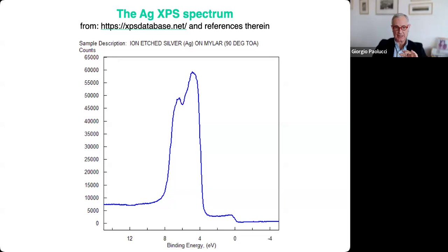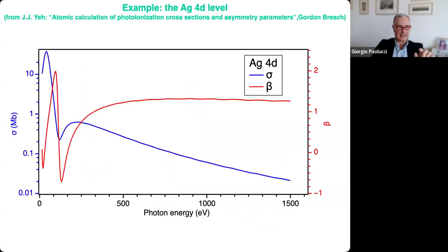And you can see that between 0 and say 3.8 eV, you get this monotonic behavior, which is what you expect from a simple metal, because that reminds you of the Fermi-Dirac distribution. And then you get the 4d levels, which are very localized in energy. The 4d level of silver has a peculiar behavior as a function of photon energy, in the sense that if you look at the cross section, forget about the red line here, which is another parameter which we will not describe, you see that you get a maximum and then a minimum in the cross section. And this is a phenomenon which is known as the Cooper minimum.